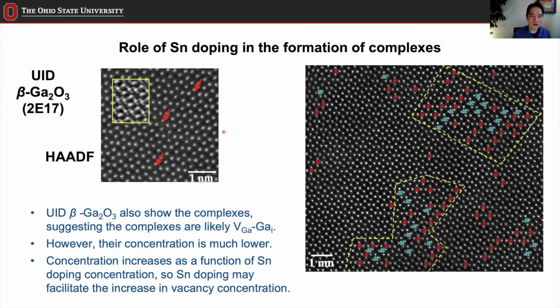What we observed in this other sample was that it also showed the formation of complexes, but much lower in number. What that means is that complexes can form even without the presence of tin atoms. So whenever we see the interstitial atom here, it should be a gallium atom rather than tin, because there's no tin in this case. But their number density greatly increases as we increase the tin doping concentration, as we saw in this figure. So tin doping really facilitates the formation of these complexes.